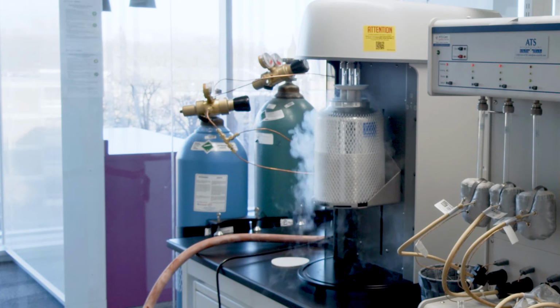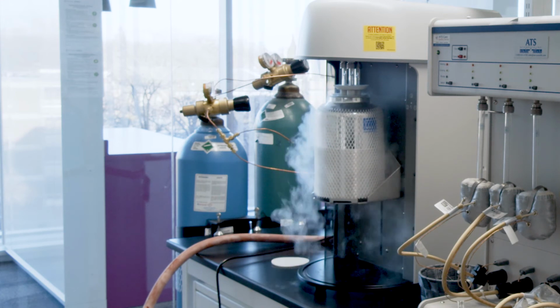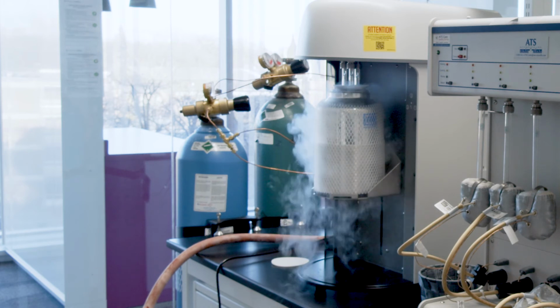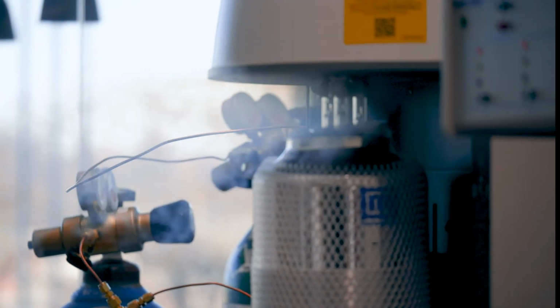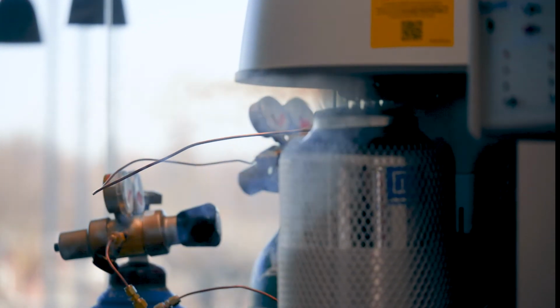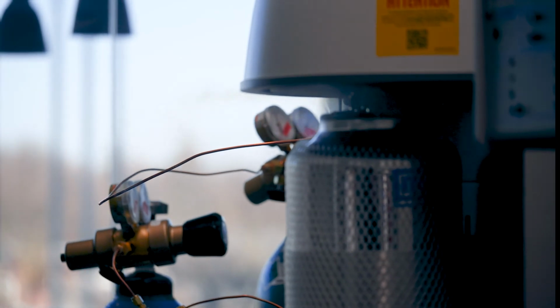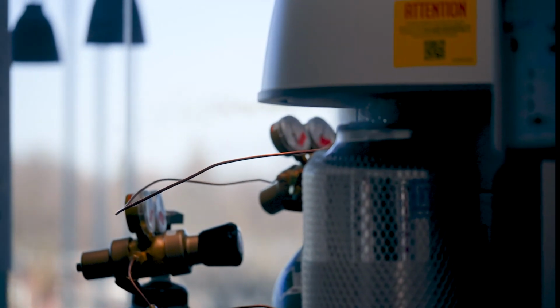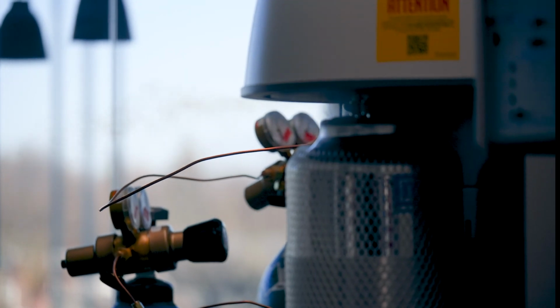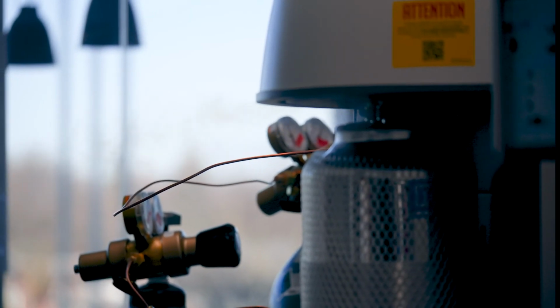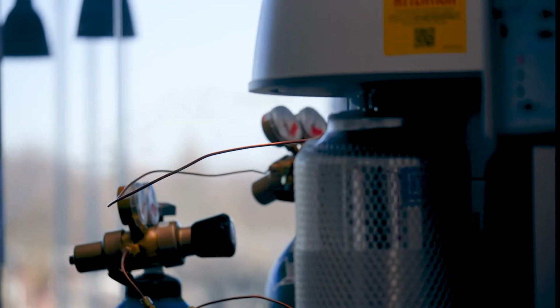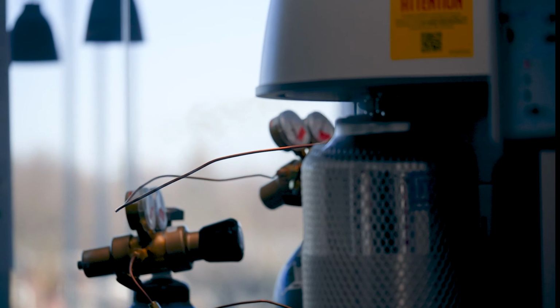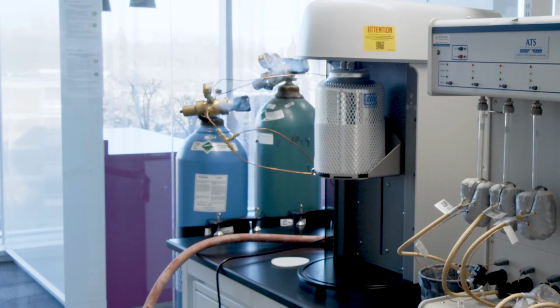So when measuring the surface area and porosity of MOFs, we do the measurements at 77 Kelvin, which is the temperature of liquid nitrogen. And we do the measurements at this really low temperature because this is the temperature at which nitrogen gas condenses, hence why the liquid nitrogen is a liquid. At this low temperature where the nitrogen gas condenses, the nitrogen gas can easily stick to the surface of our metal organic framework. When the nitrogen gas interacts with the surfaces of our metal organic framework, it can form a nice uniform monolayer on the surface. And depending on how many molecules of nitrogen gas are required to form that monolayer, we can determine the surface area and also the porosity of our material.